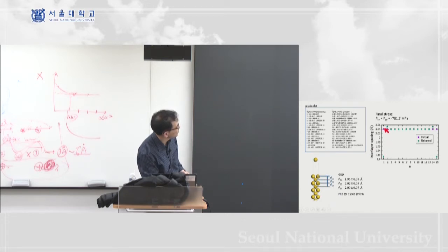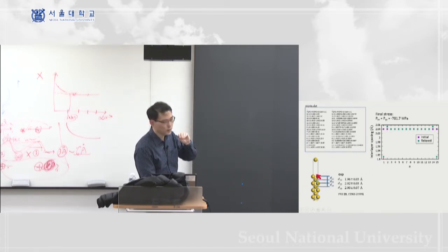So this is the spacing at the top layer, and this is the second layer, right? And you can see that this is initial. Initially, since we have the bulk terminated, every interlayer has the same spacing, right? So 2.04, which is the bulk. And then after relaxation, you can see that the first and second layer actually get closer, and it results in a smaller interlayer spacing. And then the spacing D2,3 becomes slightly longer, all right?